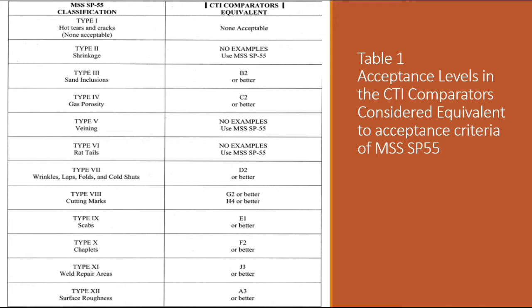So none of the hot tear, none of the crack can be acceptable based on the CTI comparator or SCRATA. Type 2 defect is called shrinkage. So basically no example. You can directly refer to MSS SP 55, which will be shown in the later slides. Type 3 is basically sand inclusion. In this, B2 or better is acceptable. Type 4, gas porosity, C2 or better can be acceptable. Type 5, veining, no example. You can directly use MSS SP 55 for reference for acceptance or rejection. Type 6, rat tail, no example. You have to directly refer to MSS SP 55, example shown in the next slide.